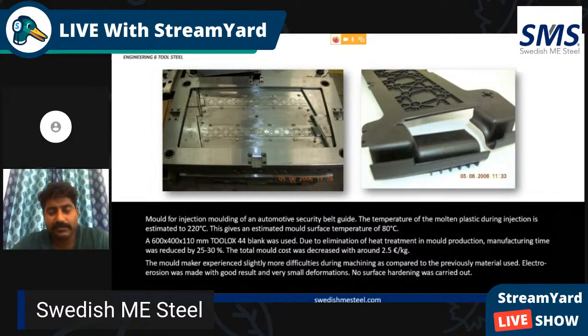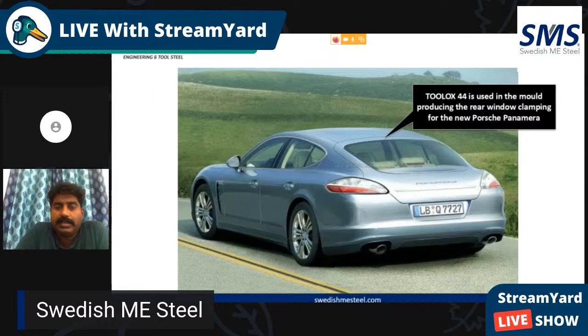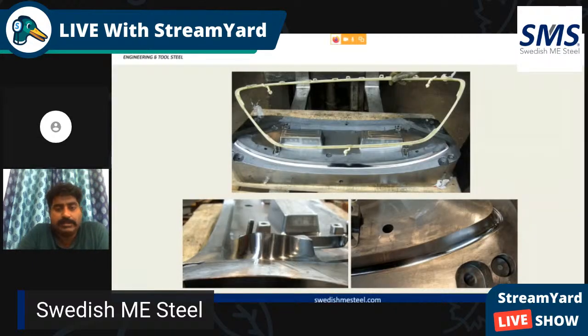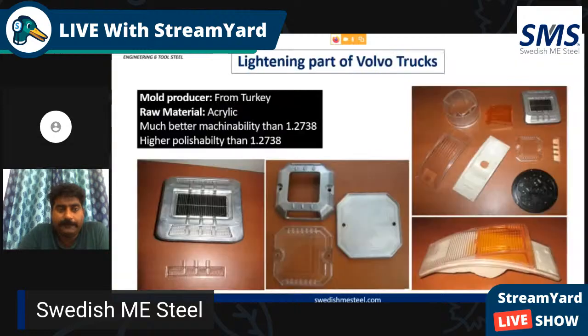If you're able to save 200 rupees per single kg, and you're using a mold where 200 or 500 kg is required, you can look at the savings that the material brings to you. And the mold maker experienced slightly more difficulty with machining, which is understandable. They'll be able to overcome that in due course of time. And Toolox 44 is used in the mold producing the rear window clamping for the new Porsche. So this is the component which we made.